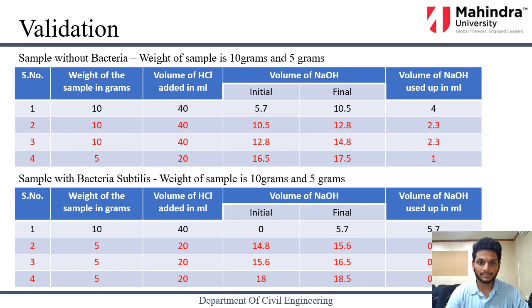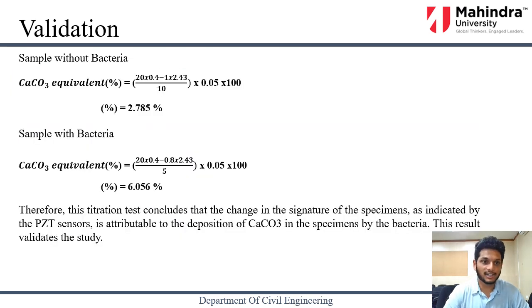We can see that the results are here, and we omitted the odd one out, which was showing some different results. We can see here that the sample without bacteria has a calcium carbonate percentage of 2.78, and the sample with bacteria has a calcium carbonate percentage of about 6.056%, which indicates that the change in signatures is indeed due to the formation of calcium carbonate by the bacterial action.